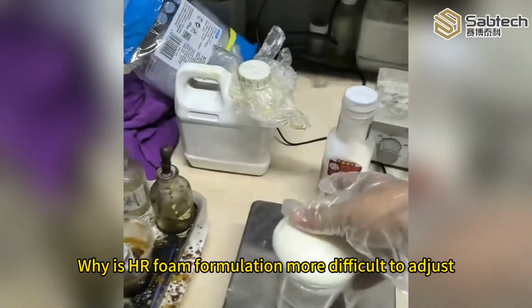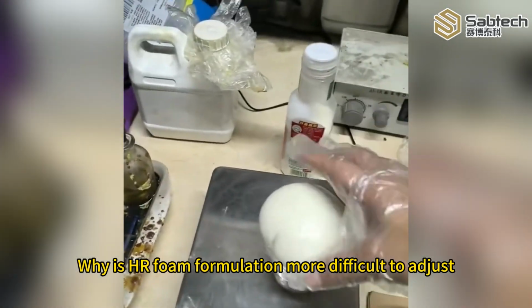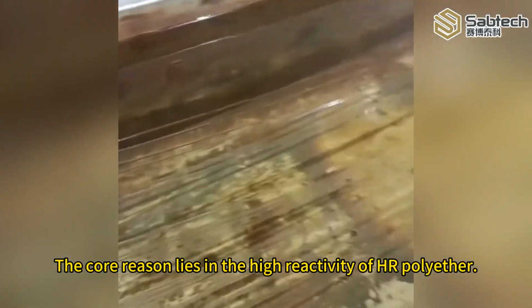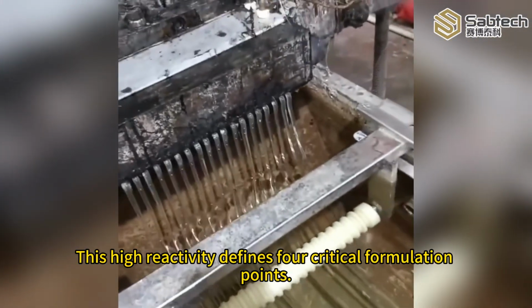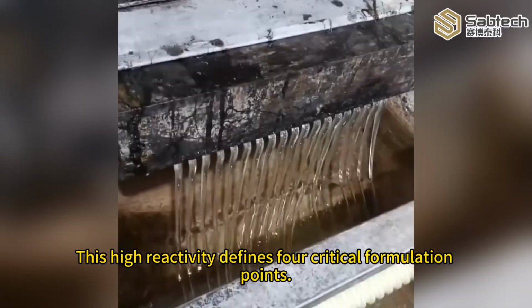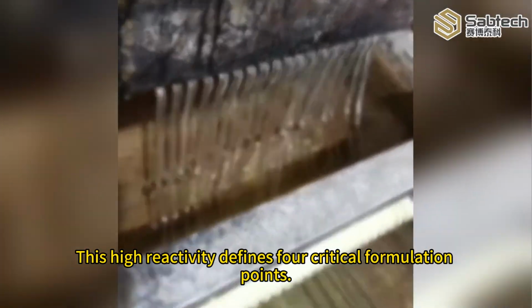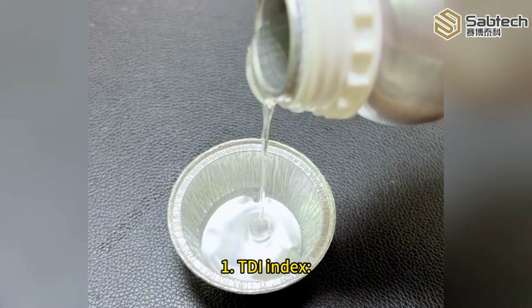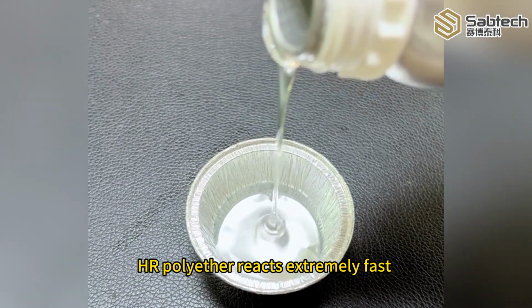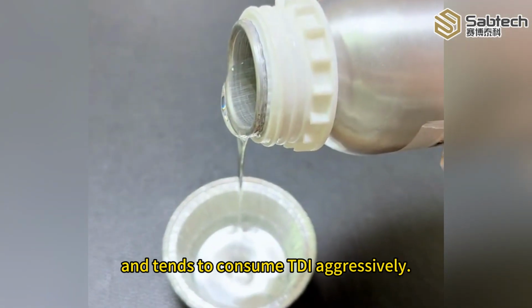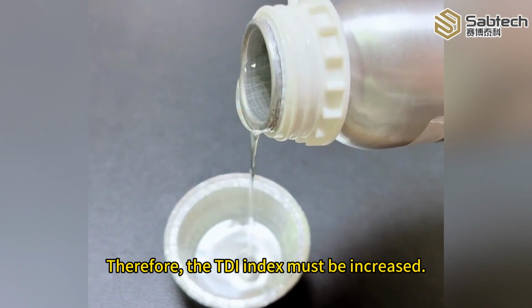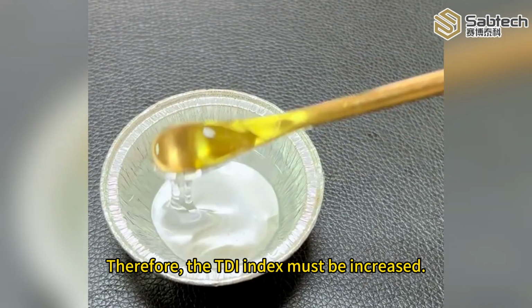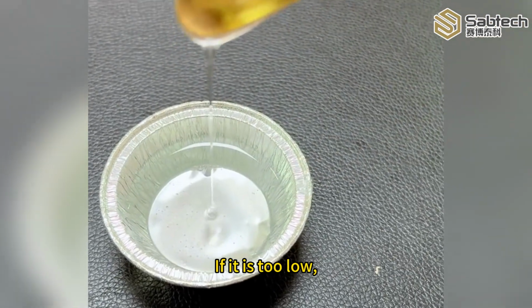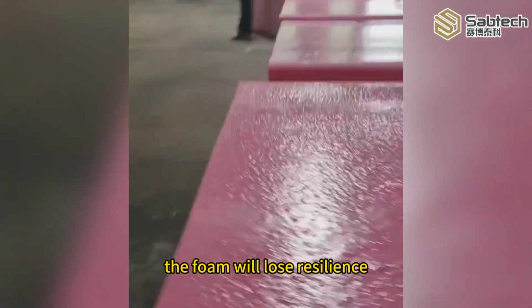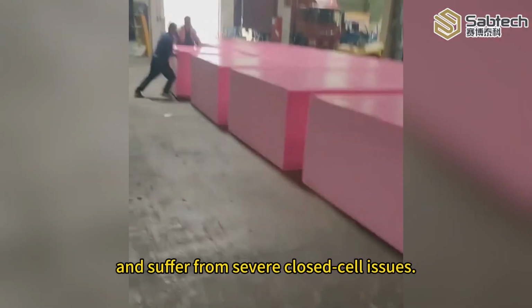Why is HR foam formulation more difficult to adjust than conventional foam? The core reason lies in the high reactivity of HR polyether. This high reactivity defines four critical formulation points. 1. TDI index. HR polyether reacts extremely fast and tends to consume TDI aggressively. Therefore, the TDI index must be increased. If it is too low, the foam will lose resilience and suffer from severe closed cell issues.